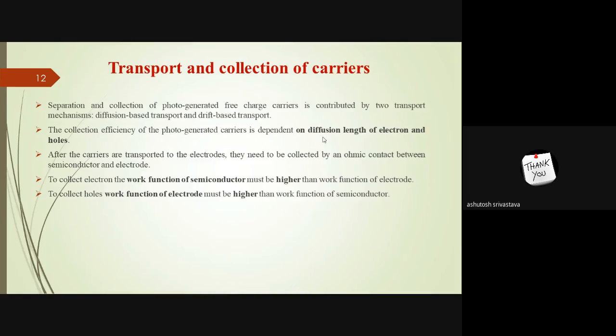And as we can all visualize, if the width of the material is more than the diffusion length of an electron, then definitely the electron will not travel to the end of the material. So this is a very important concept to be taken care of in choosing the material, because the diffusion length has to be more than the width of the absorber layer so that the electron and hole can travel to the extreme of the material and finally get collected at the end.